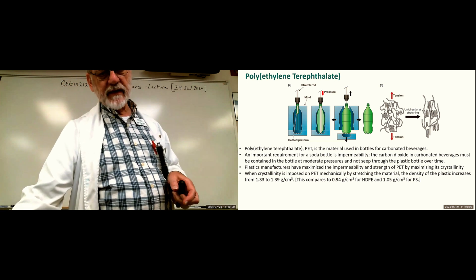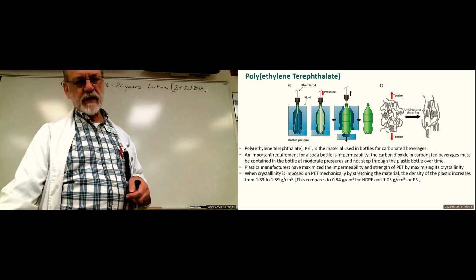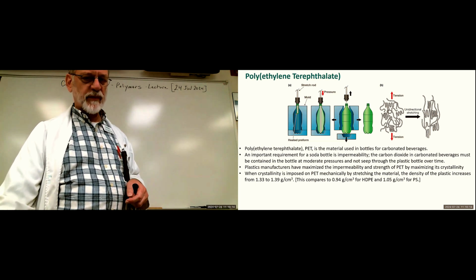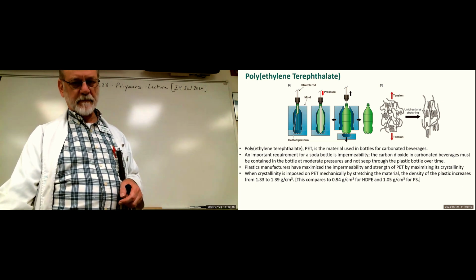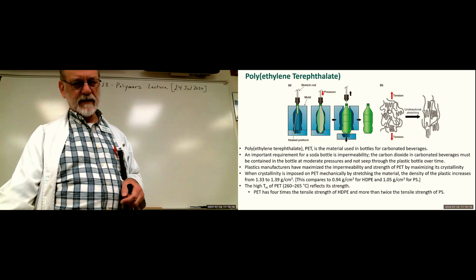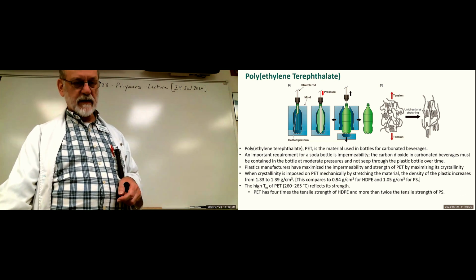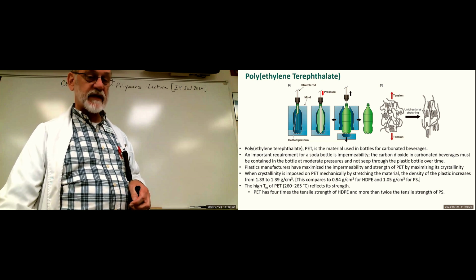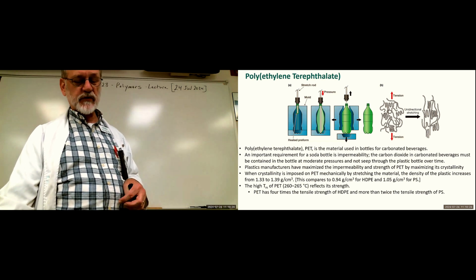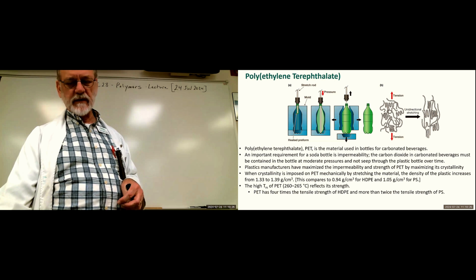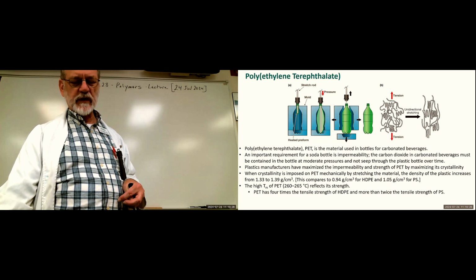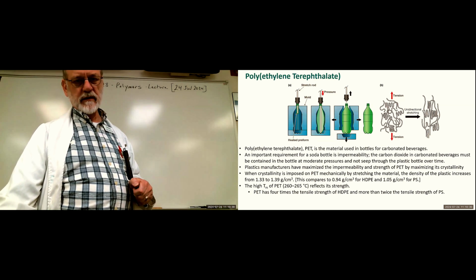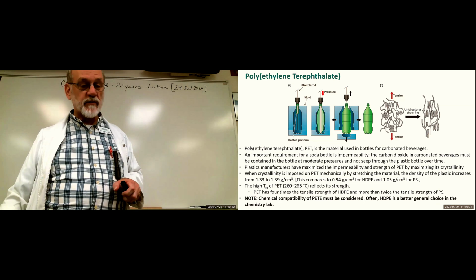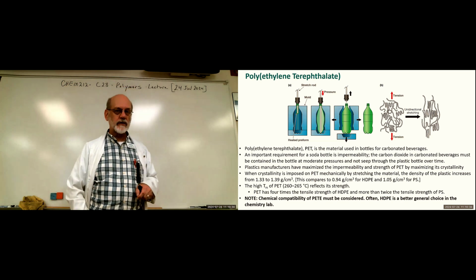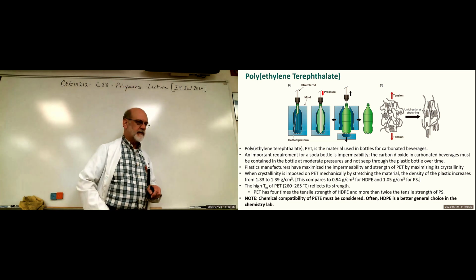Maximizing crystallinity increases the strength and decreases permeability. Okay. So PET has 4 times the tensile strength of high density polyethylene, more than twice the tensile strength of polystyrene. Interesting. I always knew that my pop bottles were rated to 100 psi. That's why we never go over 60.